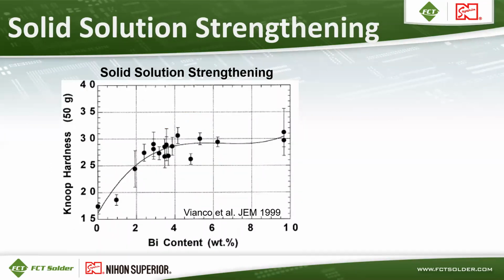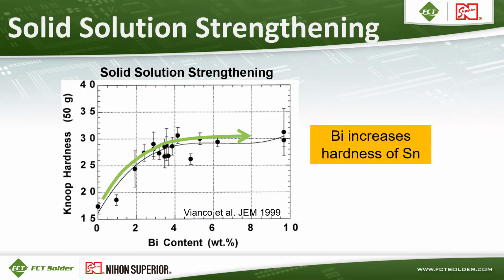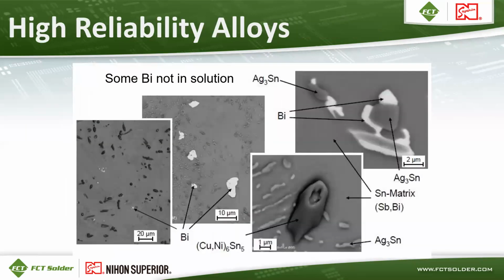So solid solution strengthening is one way to address this problem. What I mean by that is the element that you're adding to the tin matrix stays dissolved under the conditions in which it's used. It doesn't form precipitates or separate intermetallics. So in this case, what I've got is a chart of Knoop hardness with varying bismuth content increasing from left to right. So as bismuth content goes up, Knoop hardness goes up, and theoretically reliability goes up. So that's one particular element that might help with increasing reliability.